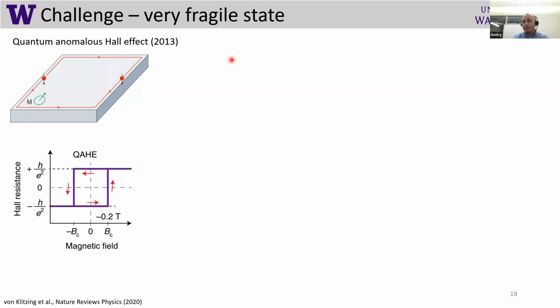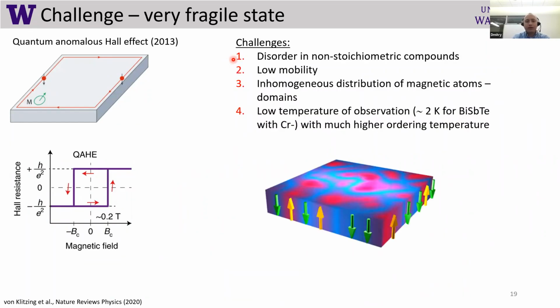So the challenge of using the quantum anomalous Hall effect for many of those applications is the fact that this state is very fragile. The fragility comes from the way people grow this material, by MBE, and actually the quality is really high. But the main limitation is that you take a topological insulator and then locally put in magnetic ions. This creates disorder, and that's why the highest temperature now is around 2 Kelvin for this material. So there are some limitations.